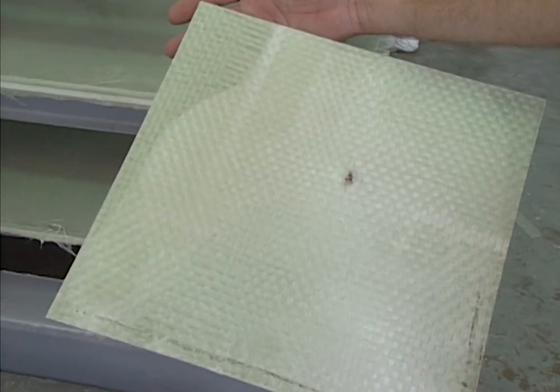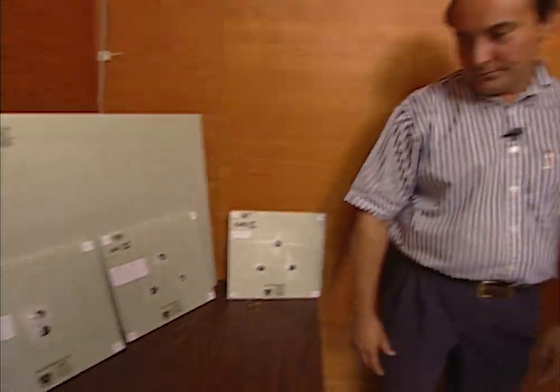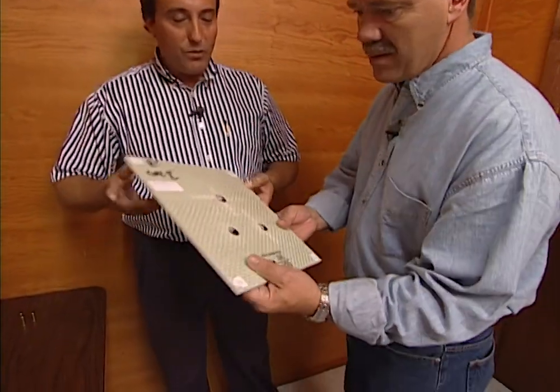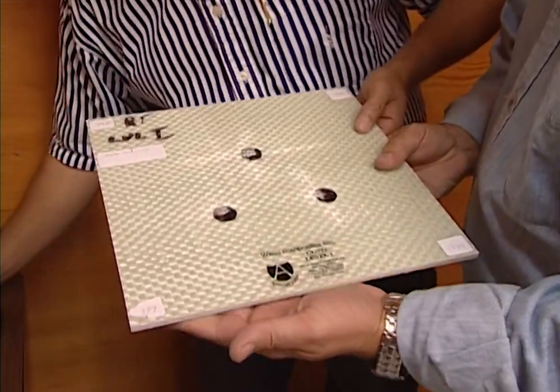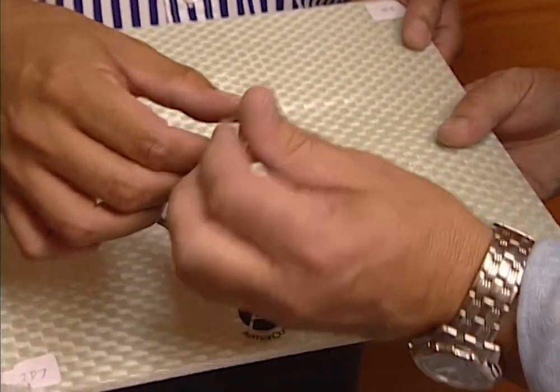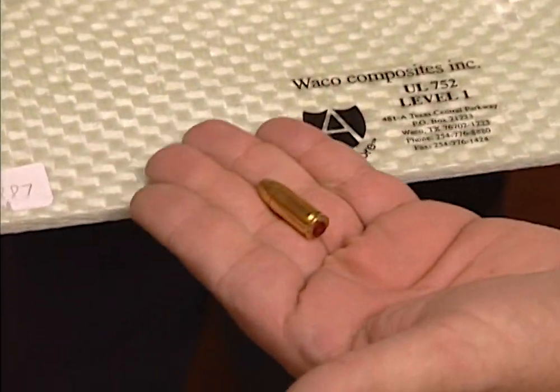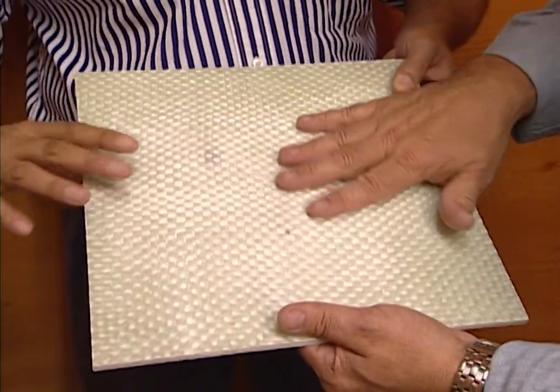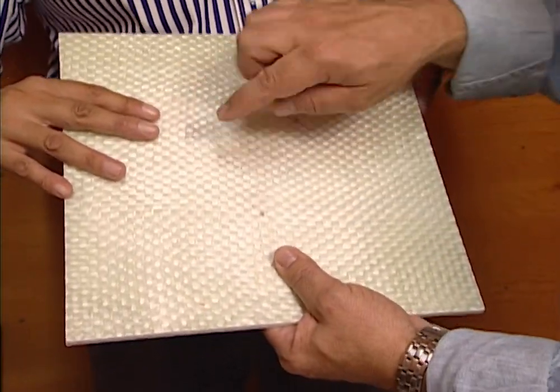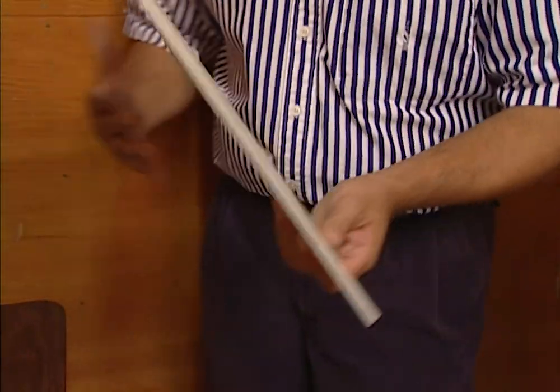The thickness of the panel depends upon the caliber of bullet you want to stop. Wayne, you make four different thicknesses of this bullet resistant material — why? Steve, we are trying to stop four different weapons here. Level one ArmorCore is a five-sixteenths-inch thick product designed to stop a nine millimeter round. Here you have three shots per one square foot panel, and you can see that we defeated or stopped the energy of the bullet. It's just humped up there, but the bullet is locked inside the panel.